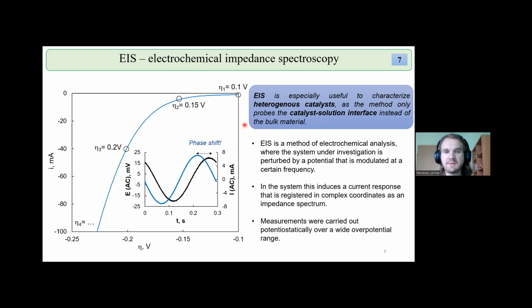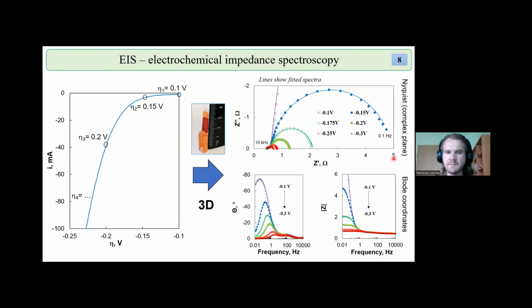So to characterize fully a single electrode in hydrogen evolution reaction electrocatalysis, we obtain electrochemical impedance spectra at different overpotentials. So this is a simple polarization curve for the sample, and shown here are the overpotentials at which the impedance spectra are obtained. And it should be noted here the steepness of the curve. And the resulting spectra obtained on a molybdenum sulfide film deposited on a foam electrode are shown precisely here.